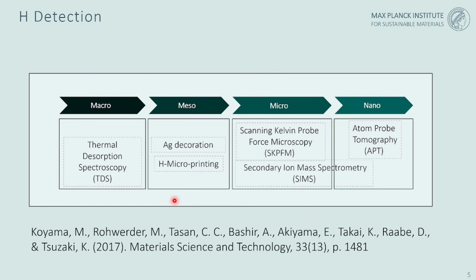There are also very nice mesoscopic methods of revealing where the hydrogen is, for instance, leaving the material, such as decoration with certain silver cyanides that lead to silver cyanide reduction and decoration of silver at the surface, and certain hydrogen-related microprinting techniques. These are very interesting methods because they allow you to show on a more microstructural scale where the hydrogen had been located, such as revealing hydrogen decoration of interfaces, for instance.